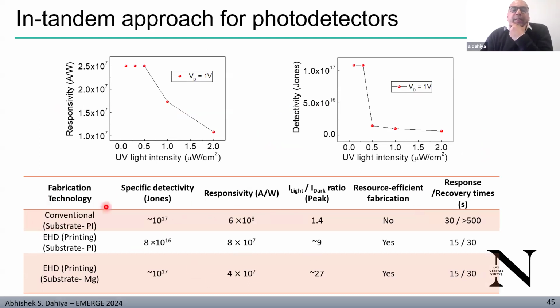So we have fabricated a similar device using the conventional fabrication approach, where we deposited titanium and gold electrodes. This is through EHD on flexible and transient substrates. These are the numbers for detectivity, responsivity, on-off ratio, and response and recovery times.